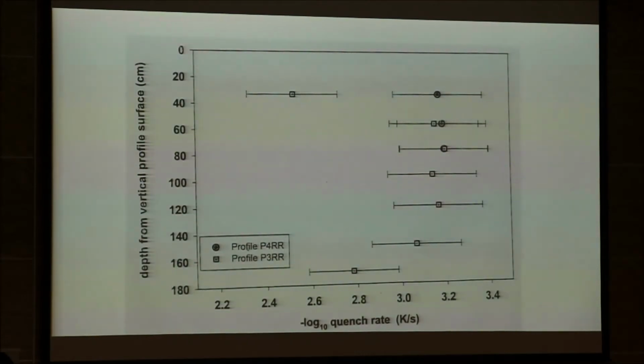And these are the cooling rates we estimate by going from the top to the bottom of a glassy lava flow. This is the minus the log of the quench rate. So relatively fast cooling rates at the bottom and at the top of the lava flow, and then slower cooling rates in the interior. By the time this was going on, there were all kinds of really bright people thermally modeling all these things and giving you the answer, but they had nothing to calibrate their models on. So this is just an honest experimentalist saying, here are the cooling rates you have to get as a result of your model for cooling of this lava flow. And there are 100 of them in all, so it's a great time.